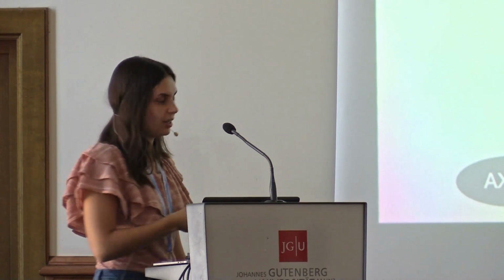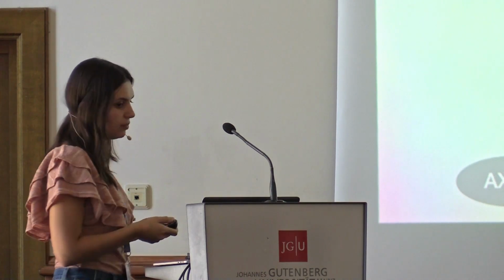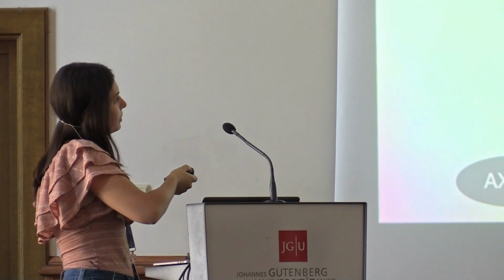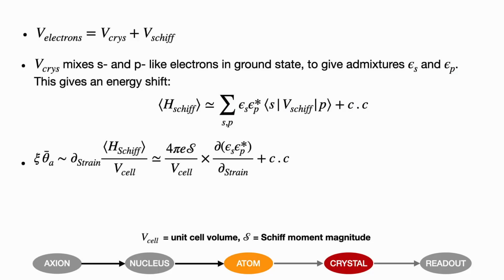And we note these admixtures by epsilon. And the result is that we get an energy shift that depends on the admixture, which comes from your piezoelectric crystal structure and your Schiff moment potential. Now, in order to understand the scaling of the piezoaxionic tensor, what happens here is that the piezoaxionic tensor depends on your Schiff moment potential and how that potential changes as you strain your crystal. And if you were to do this calculation, you would see that this would give us two parts. The first part that depends on your nuclear properties primarily, so on your Schiff moment, and the second part that depends only on your material properties, so on your admixture of S and P-like orbitals in your ground state. And this here we've calculated to be an order 1 factor.